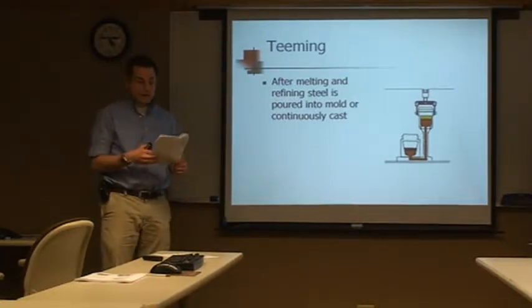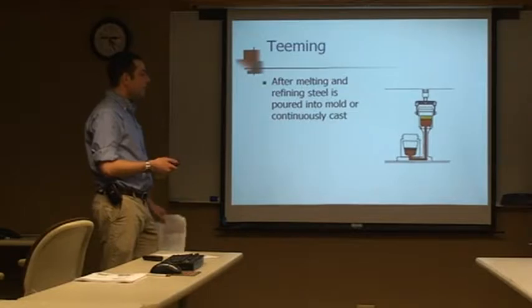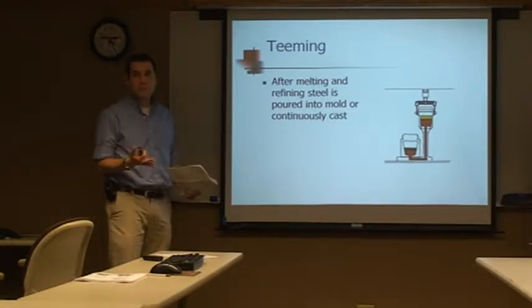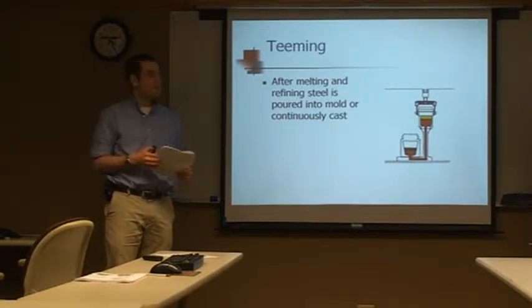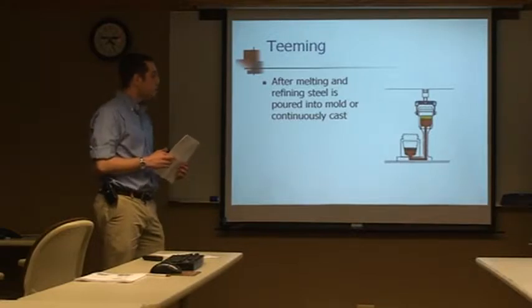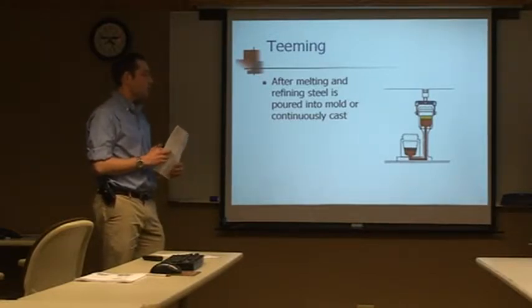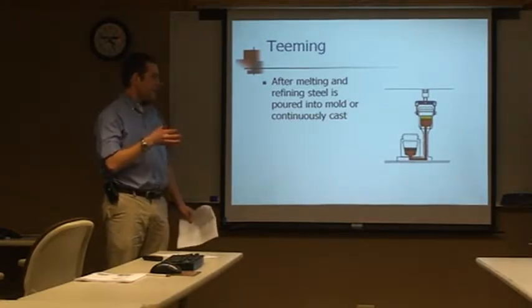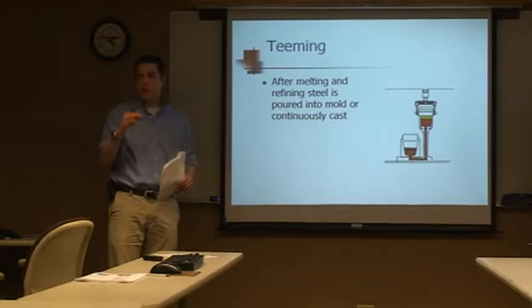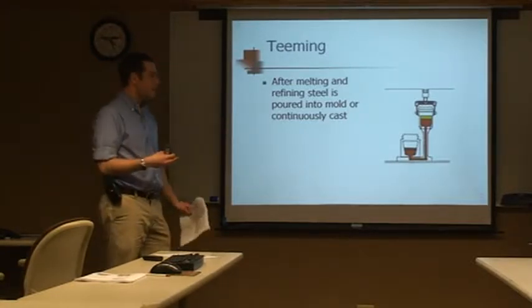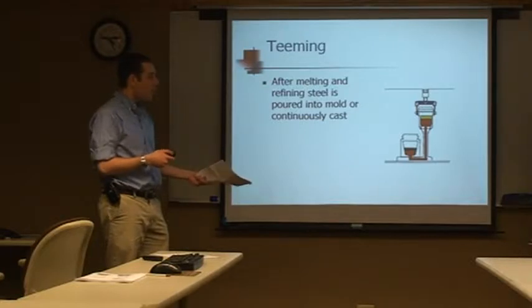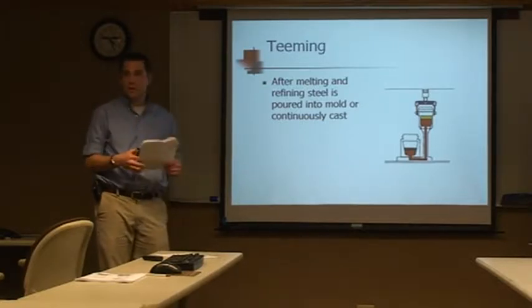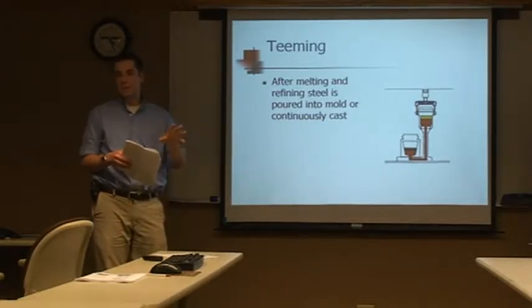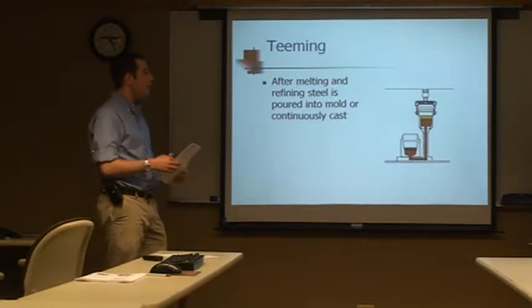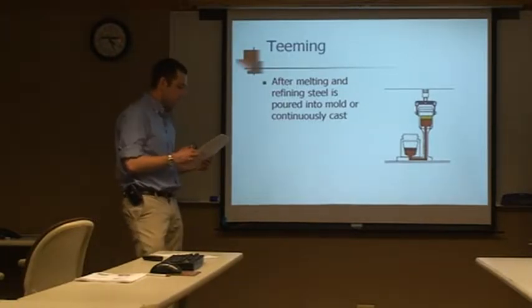teeming hardware, because the liquid steel is extremely hot, almost 3,000 degrees Celsius, or Fahrenheit, I'm sorry. So we want to keep that kind of hot metal from eroding away the mold and the other teeming hardware. We'd rather have it do damage on the ceramic lining that we throw away each time.